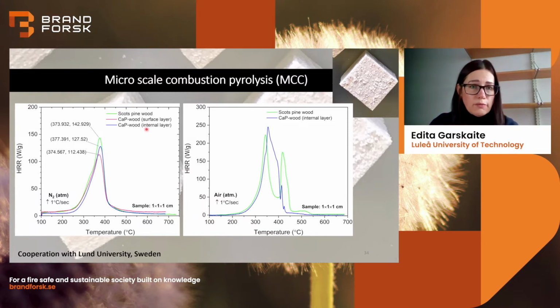What we observe, the green curve is unmodified wood, and when we compare with calcium phosphate from eggshells mineralized wood, we get that this mineral actually has an effect, and it reduced the heat release rate. From the surface we have the highest reduction, and it probably also has to do with the highest amount of mineral we have on the surface.